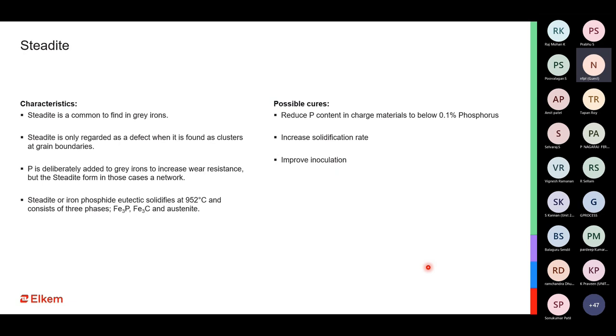How do you control it? You control it by reducing the phosphorus content. That is number one. And definitely number two, by improving inoculation. You have a much higher number of grain boundaries, so that even if you get steadite, it should be uniformly distributed and we do not have too much graphite or steadite segregation causing problems to our casting.